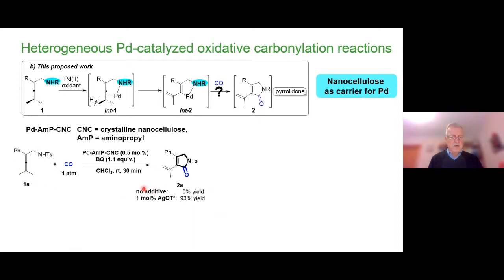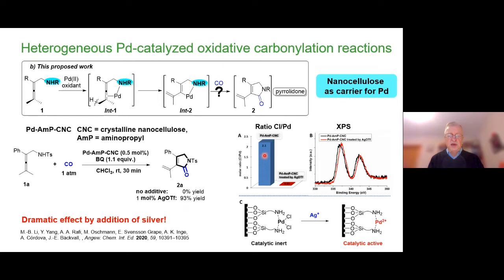And look here, interestingly, we found that when we run it under normal conditions, we got nothing, 0% yield. And when we added just 1 mole% of silver, we got a 93% yield of this desired product. So the question is, what is silver doing here when it has this effect in this very small amount? So it's a dramatic effect by the silver. The role of silver, we believe, is that it strips off the chlorides on the catalyst. So we have measured the ratio chloride to palladium before adding additional silver. It's about 2 here. And then after additional silver, it's almost 0, this ratio.